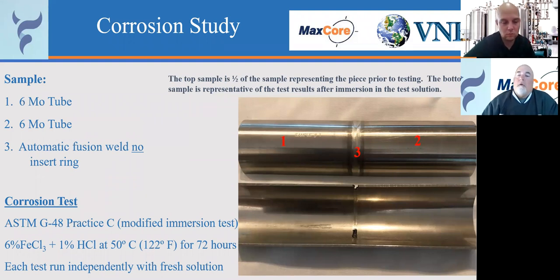Now what we've done here, if you look at this top sample, this was a piece of tube that was just done a straight fusion weld on. Then we split this tube long ways. We kept the top piece as just a controlled sample so we could see how it looked before the corroding solution. And then we put the bottom piece in the corrosion solution. And you can see this particular weld area started to be impacted in this particular area. It was basically eaten up and eaten away. And it's here at this location. It would have been probably eaten up pretty well all over if we'd left it in there longer.